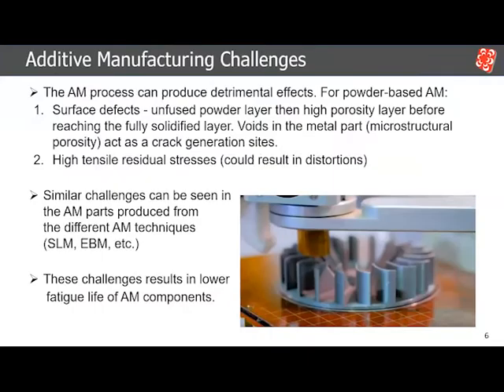Let's talk a bit about additive manufacturing. Different additive manufacturing techniques have different problems. The majority of additive manufacturing techniques result in components that have challenges to their fatigue life. For example, for powder-based additive manufacturing, you have major surface defects in the form of unfused powder layers, high porosity, and even inside the material you still have voids. All of these are crack initiation sites. In addition, the additive manufacturing technique itself generates high tensile stresses. When you put these two factors together, that is the reason why additive manufacturing components tend to have much lower fatigue life compared to traditionally manufactured parts.